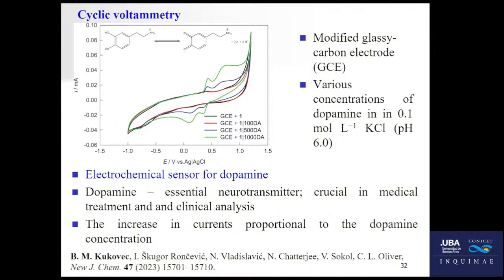So we used different concentrations of dopamine, and this electrode which was prepared as I explained, and you can see the results here. So what are the results? You see the concentration of dopamine is increased here. If you look at it here, it's a smaller concentration, and at the higher concentration you see that the peak currents increase with increasing the concentration of dopamine in the solution. And that was a linear increase.